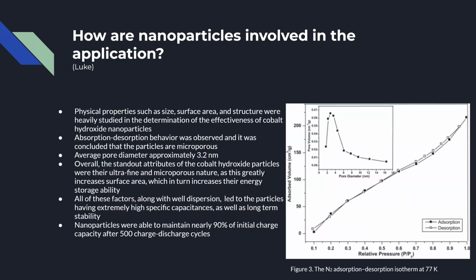So now we'll look at how the nanoparticles are actually involved in the application. It's primarily the physical properties of the particles that allow them to be viable for energy storage, such as their size, surface area, and structure. The absorption-desorption behavior was also observed. It was concluded that the particles are microporous. And if you look at the small graph off to the right, it compares pore diameter to pore volume. And the average pore diameter was approximately 3.2 nanometers, which is right in that sweet spot where the pore volume is the highest, which leads to a high absorbed volume as well.